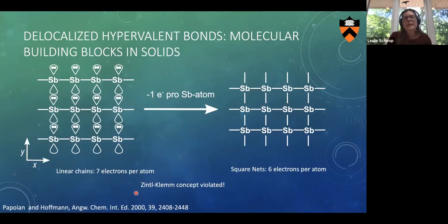Hypervalent bonds have been described in solids, and this was again by Roald Hoffmann in 2000. There he has a paper where he says there are some materials which have linear chains of antimony with seven electrons per atom, or square nets with six electrons per atom of antimony. And these violate the Zintl concept, sometimes called Zintl-Klemm concept. So it doesn't match with the bonding order and everything we discussed earlier. And then he concludes that they're hypervalent. But why are they hypervalent? So let's look at the square nets. Antimony usually formally has five electrons.